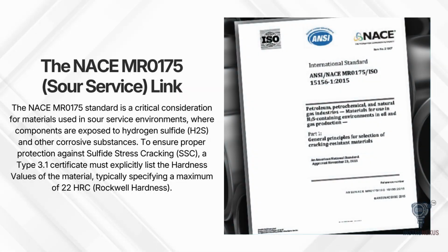A special note on NACE MR0175, the standard for sour service. This is a critical consideration when materials are exposed to hydrogen sulfide, H2S, which causes sulfide stress cracking, SSC. If your project is sour, a standard 3.1 certificate isn't enough. The 3.1 certificate must explicitly list the hardness values of the material. Typically, we are looking for a maximum of 22 HRC, Rockwell hardness. Without this specific data point on the certificate, you cannot verify if the material will survive the corrosive environment.